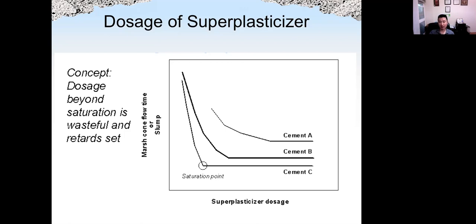However, beyond a certain point of dosage, further increase of superplasticizer, there's no change in flow time. So that means at a certain point, we have fully saturated cement paste. We call that the saturation point for superplasticizer. Beyond that point, it just wastes more superplasticizer. It will not increase the slump.